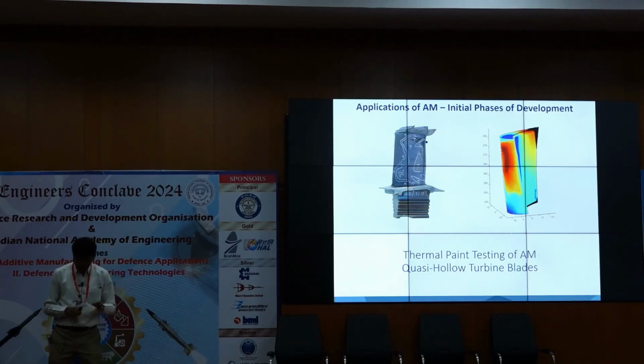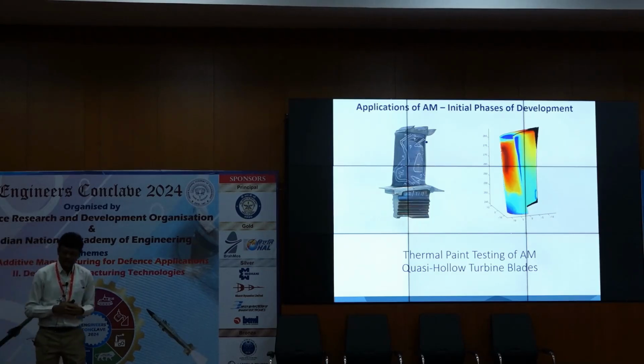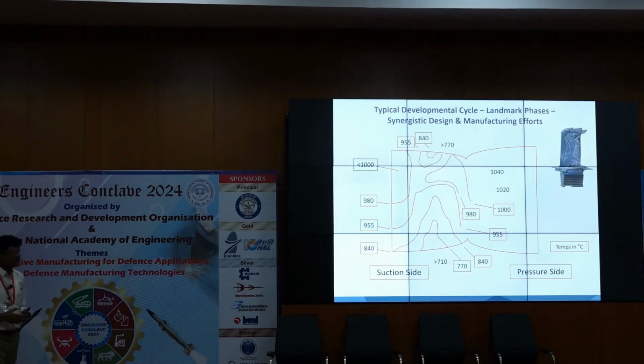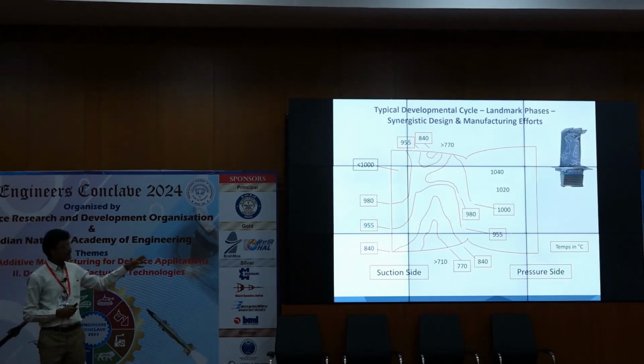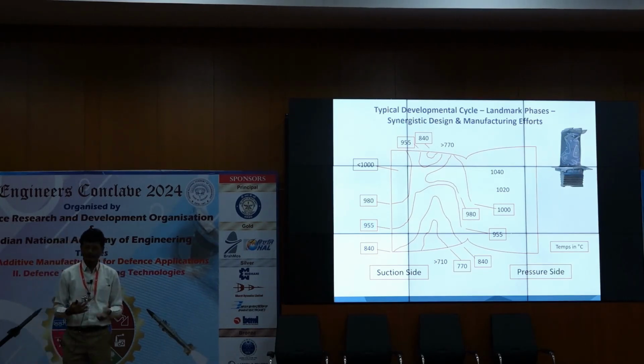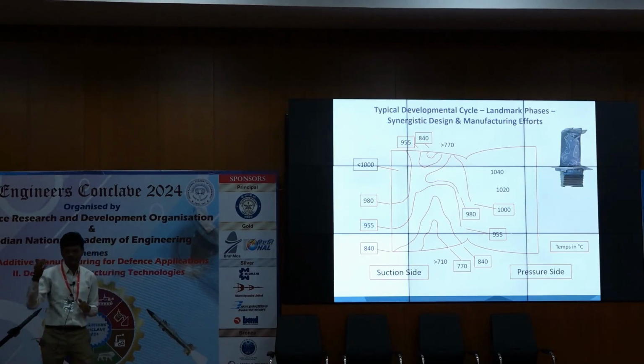But if you were to use the metal additive manufacturing and make this turbine blade and spray it with temperature sensitive paints and check it in the heat transfer test rigs, you can get these isothermal plots on the surface which indicate basically the heat transfer distribution on these quasi-hollow surfaces. So this kind of information, which is absolutely valuable, which is only possible after making of the components, can be obtained right in the early stages as long as the conductivity of this material is very close to the conductivity of the material out of which the eventual part is going to be made.